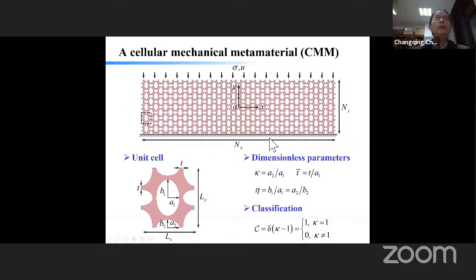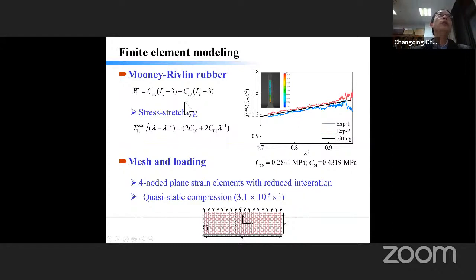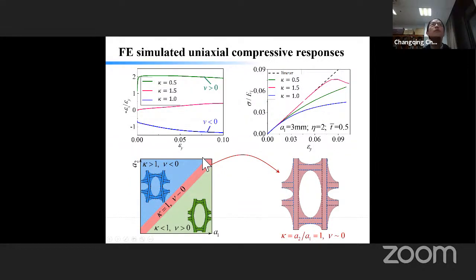So now I'm going to show you the finite element simulation of this kind of mechanical metamaterial under uniform compression in the vertical direction. The material is made of rubber. We use a Mooney-Rivlin constitutive model. We run experiments in uniaxial tension, and we can calibrate the material parameters C10 and C01. Because we consider a two-dimensional case, we use four-node plane strain elements with reduced integration. This is a static loading, so we use quasi-static compression, and the strain rate is very low, 10 to the minus 5 per second. Now I'm going to show you the simulated results.